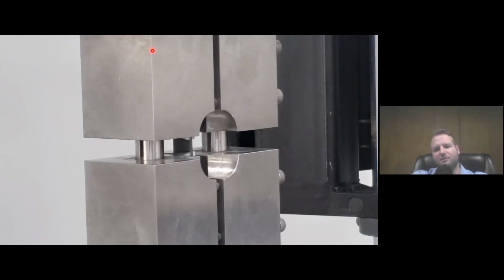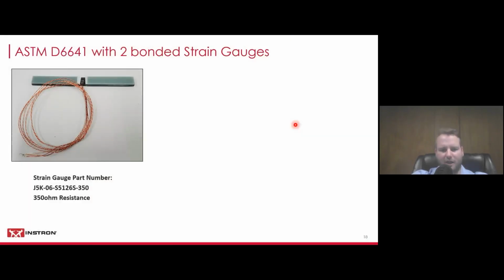You're going to see this sped up in the beginning of the video, and then it will slow down right before the break. When you see the fixture coming down a little bit, that is a lot of seating in the specimen and also some of the compression going on, and then we'll slow it down right before the break. So you can see the compliance and the seating happening here, and then at the end when the break happens. That's what a typical ASTM D6641 test looks like.